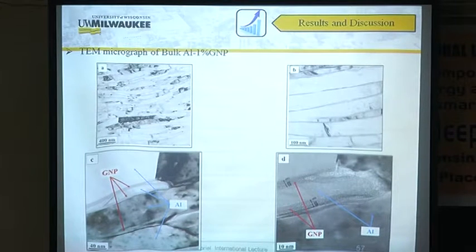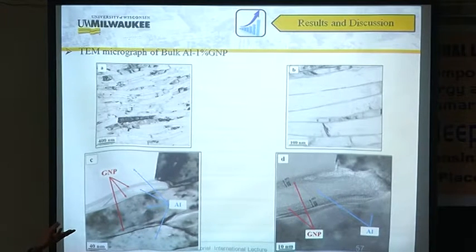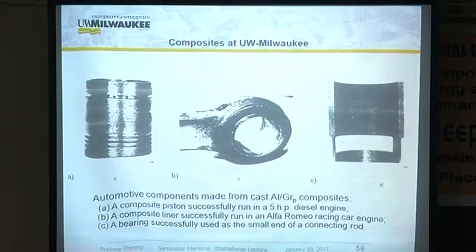The challenge is, I still have these oxide particles, and I hope one of the students can figure out how to do powder metallurgy of aluminum without alumina. And then the graphene platelets are at the grain boundaries, they are not within the grains. That's the challenge in this field. You will not get Orowan strengthening. You will still get some strengthening and stiffening, but not as much. So this is a challenge for powder metallurgy people: how to do it right so that you have nanographene within the grains.